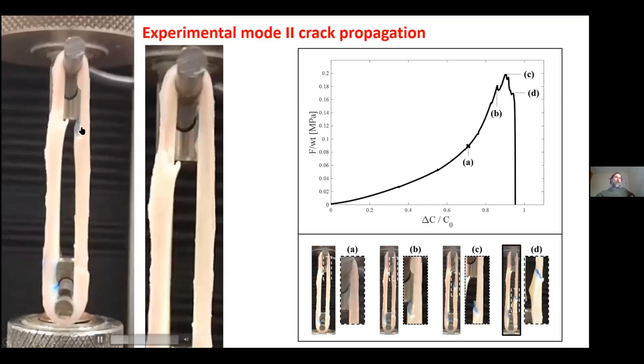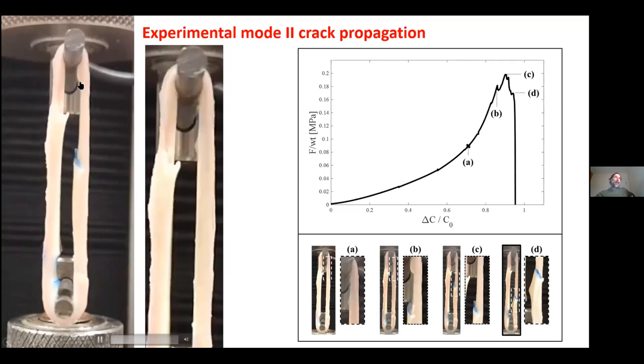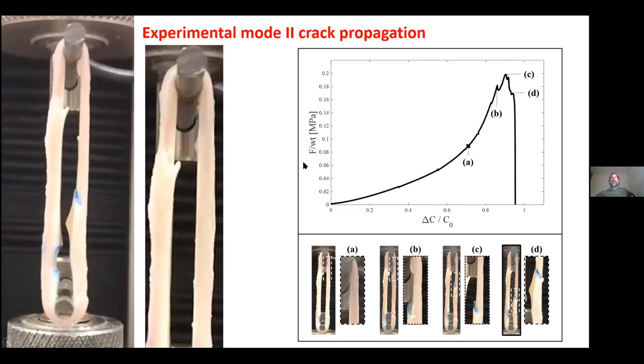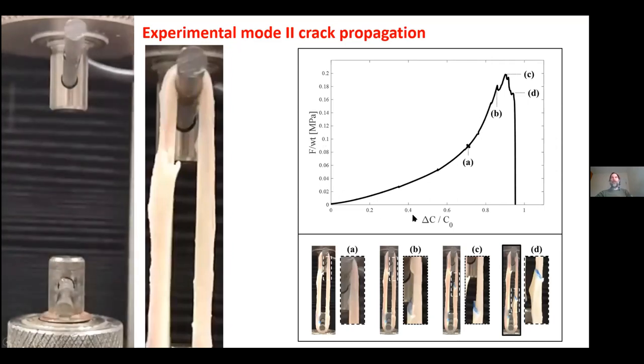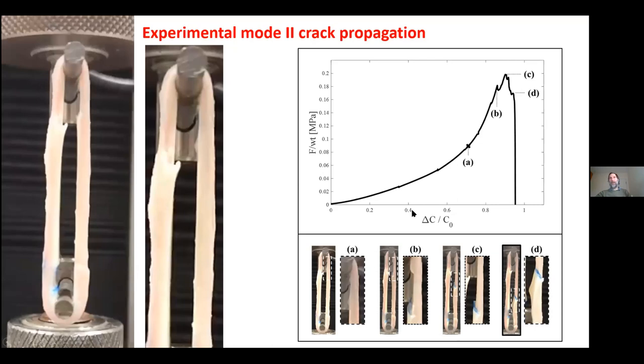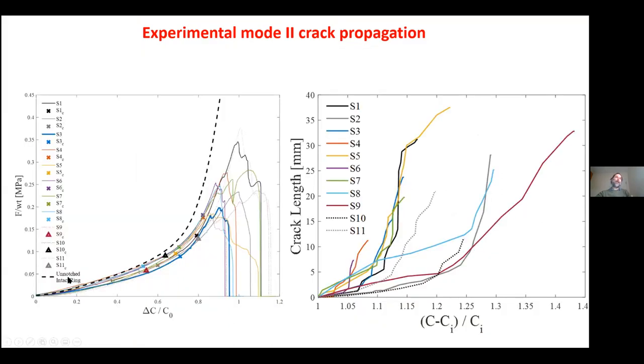So here you see an initiation and then a pure shear crack. So even though we cut the notch in the radial direction, the crack would not grow in the radial direction. The crack is turning and growing in this direction. We measure the force and the circumferential strain in the artery. And this is the point of initiation. And eventually this is the final fracture. And this was very repeatable. We did, I think, 15 tests and we got the exact same pattern every time. Every single time we got a shear crack.